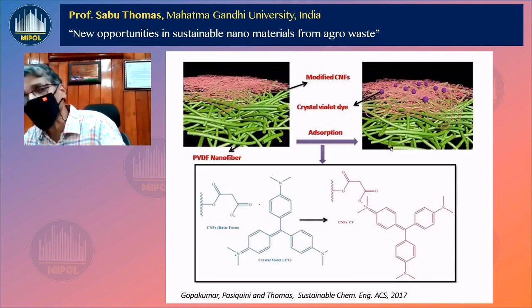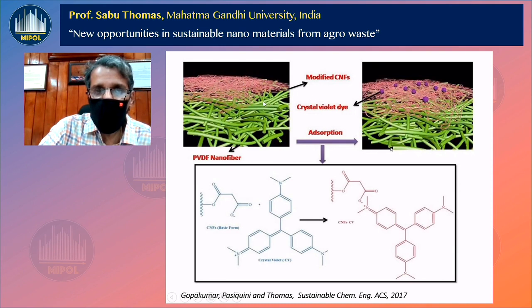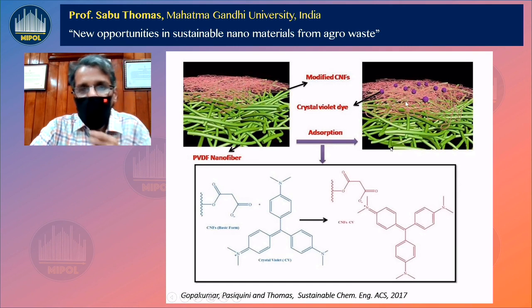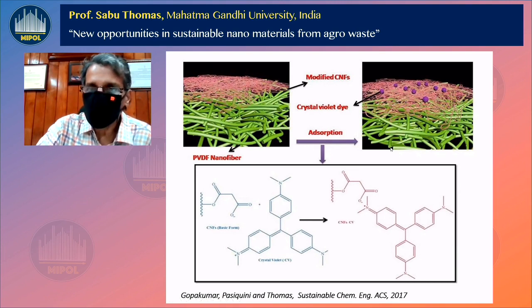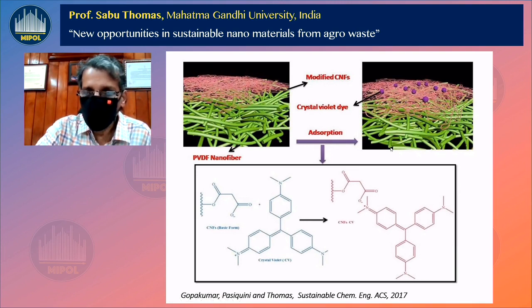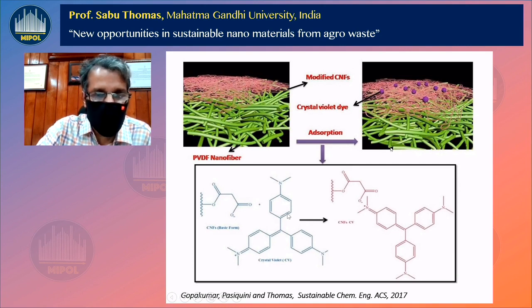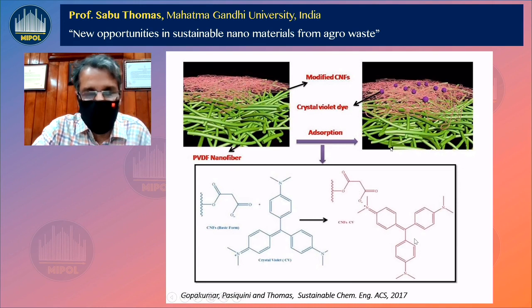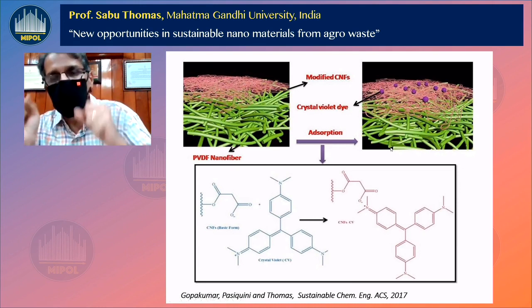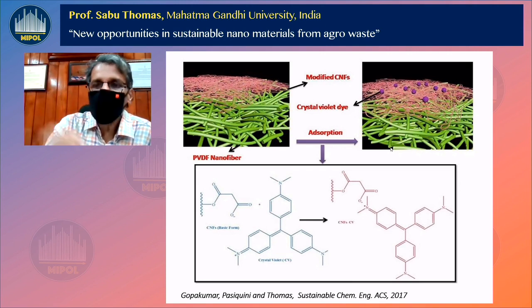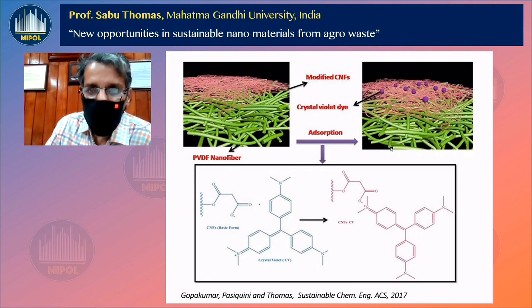And you might ask why this happens. Look at when you pass water through this filter, all these crystal violet dye molecules are being separated by the filter. And when you do chemistry on the surface of nanocellulose, you have a COO minus group. And the COO minus group can have electrostatic interaction with crystal violet. And this electrostatic interaction really helps to remove crystal violet from the impure water.